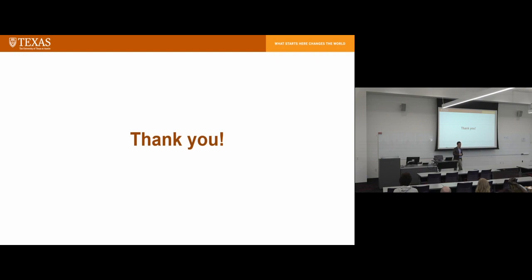I didn't show you the results. Actually, even for a 30 millimeter sample, the beginning of the sample, the quality is always worse than the end. So there is an effect. But if you're talking about roll-to-roll peeling, we can discard the first few centimeters of material. Yeah, and then we can just focus on the rest. That's a good question.